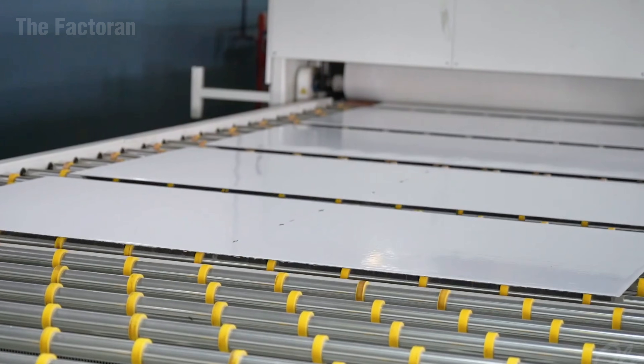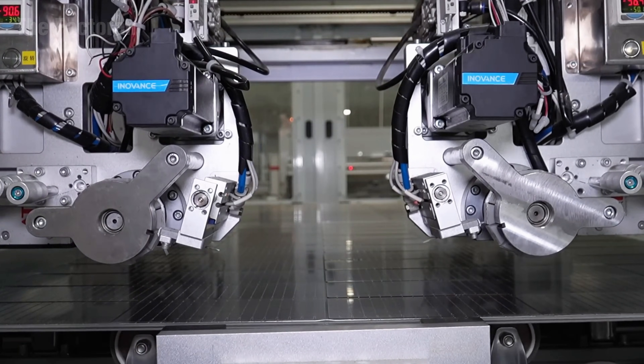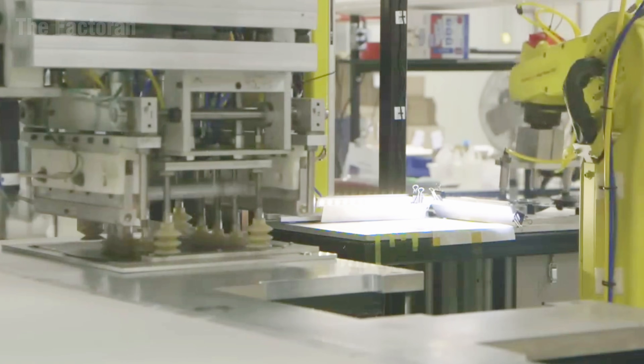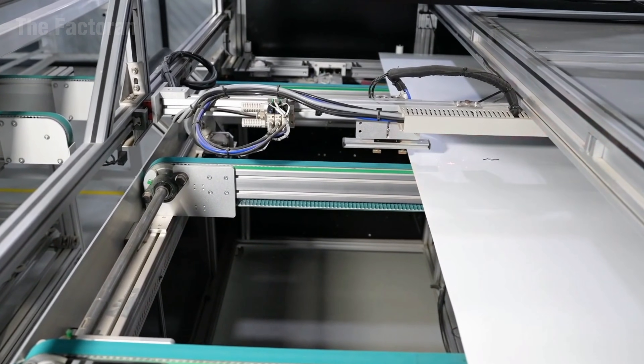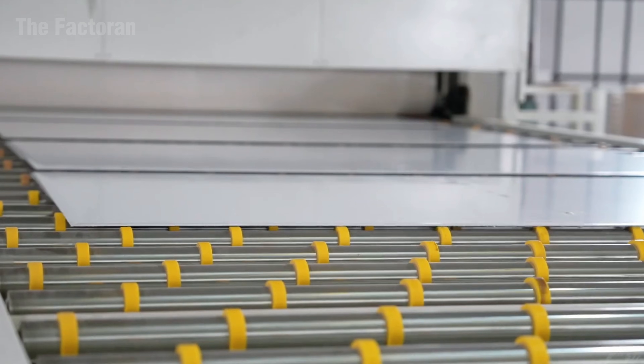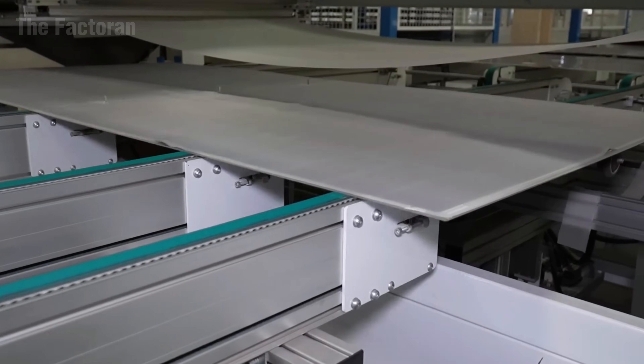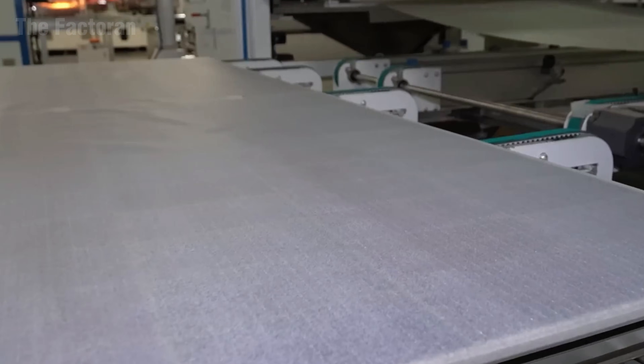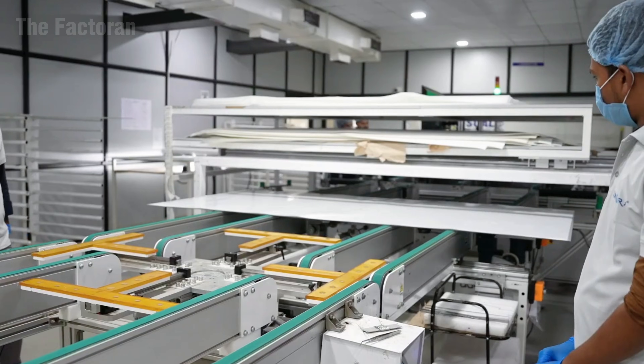When the layering process is complete, another sheet of EVA is added, followed by the insulating backsheet that seals the rear side of the module. During the hot press phase, high temperatures cause the EVA to soften and fuse, forming a durable bond between all material layers. The molten polymer encapsulates and stabilizes every photovoltaic cell, creating a unified structure that resists moisture and maintains stability against temperature fluctuations for decades of operation.